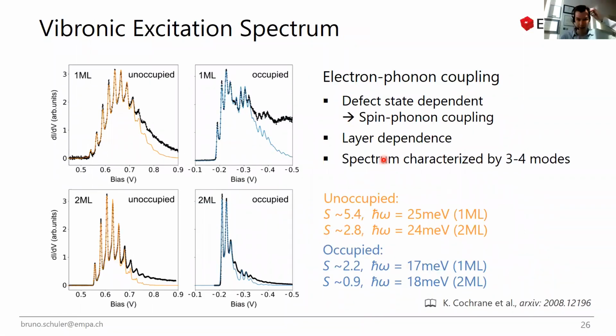Now, these are the vibronic excitation spectra, which I mentioned before. And here, I think it's quite interesting how these compare to each other. So how the unoccupied state and the occupied defect state react if you populate them with an electron or hole, and how the atomic lattice reacts to these electronic excitations. This is shown here on the top. So for one monolayer of tungsten disulfide, you see this repeating pattern. Here are the values given. So we see one strong resonance at about 25 milli-electron volts with a Huang-Rhys factor, which quantifies the electron-phonon coupling, on the order of 5.